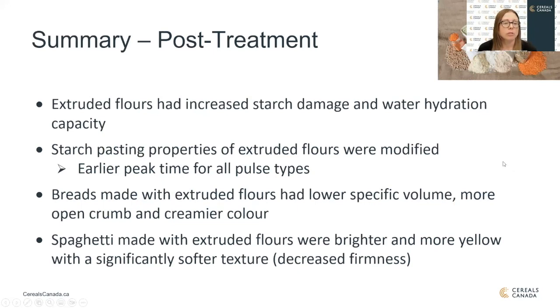So to sum up this activity, the extruded flours increased starch damage and water hydration capacity. Starch pasting properties of extruded flours were modified. We saw an earlier peak time for each pulse type. The breads made with extruded flours had a lower specific volume, a more open crumb structure, and creamier color. And the spaghetti made with the extruded flours were brighter, more yellow, and had a significantly softer texture.